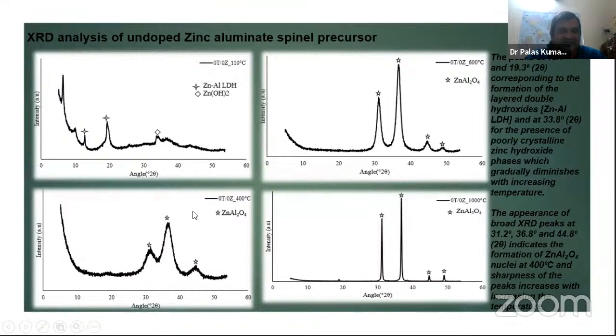With increasing temperature from 400 degrees centigrade, peaks evolve, centered at 30, which is a diffused one, however, 36 and 45. This corresponds to the formation of zinc aluminum spinel, and with increasing temperature the peaks become more intense and sharper, and at 1000 degrees centigrade the sharpness is the maximum among these four temperatures.